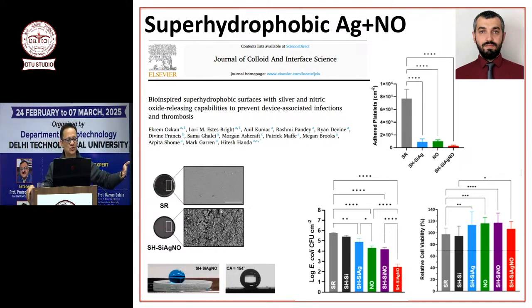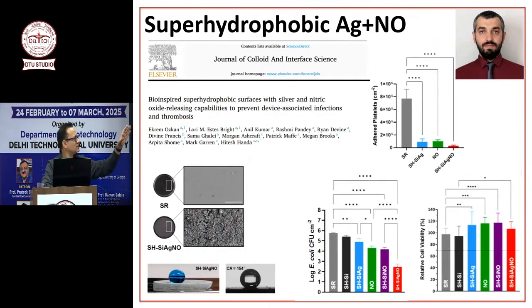So, you know, silver is a standard used in industry right now. So we thought, why not do a surface that's a combination of silver and nitric oxide and super hydrophobic. So it's a super hydrophobic, silver releasing, NO releasing surface. And we did a lot of studies. It's a good journal. And we saw that the combination was not cytotoxic. In the last graph, we were able to reduce infection. The combination of everything, silver, NO, super hydrophobic, was better than anything by itself. And it also prevented clot formation on the surface because of super hydrophobicity and nitric oxide. Not because of silver, because silver has nothing to do with clotting, but super hydrophobicity and NO prevented clot formation.